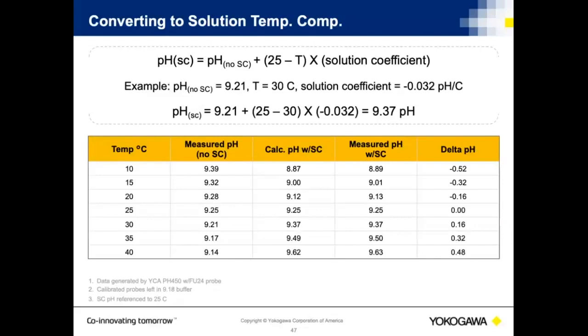Converting back and forth from solution temperature compensation. You notice at 25 degrees C, there is no difference. But as you move away from 25 degrees C, you will see a change. If you move from one measured value at 25 degrees C to 40 degrees C, it's a significant difference that can be realized in the actual pH.